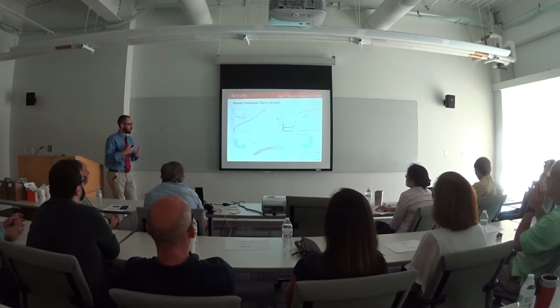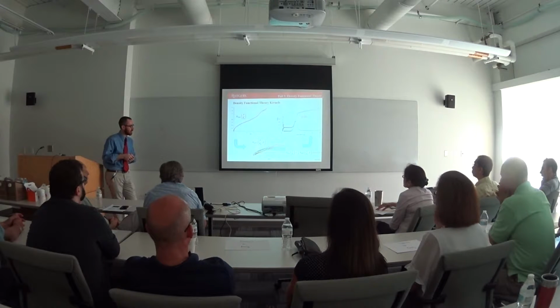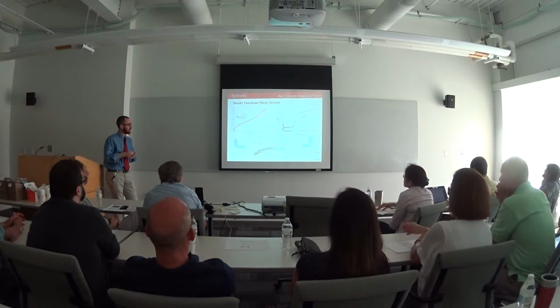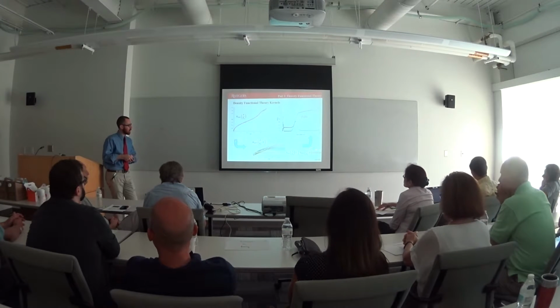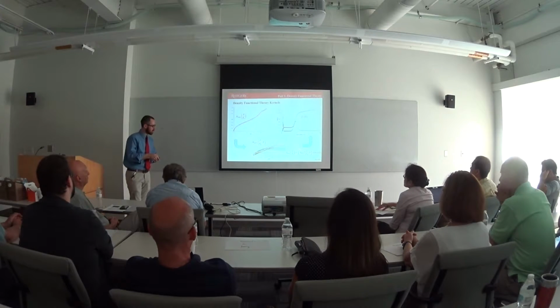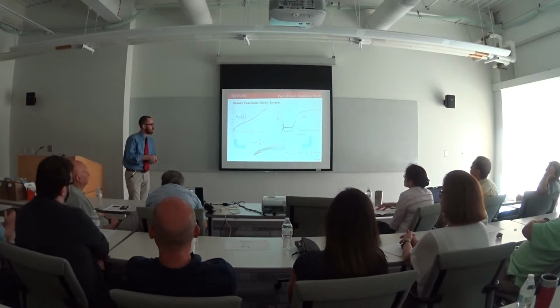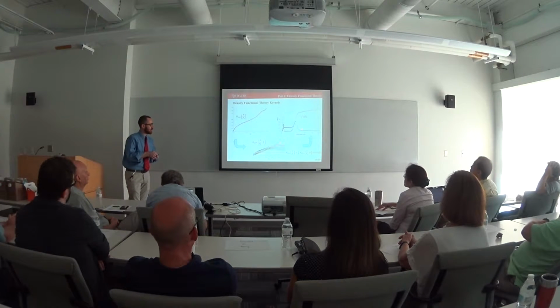So if we take a bunch of these theoretically calculated isotherms and we put them together in something called a density functional theory kernel, this kernel is used to analyze a single adsorption isotherm, such as this one shown here, by fitting something called the integral adsorption equation. And so this is our experimental isotherm, which is the convolution of our kernel and the pore size distribution. So when we put these two together, it spits out the pore size distribution. And in this case, we have pores around 5 nanometers and something else.